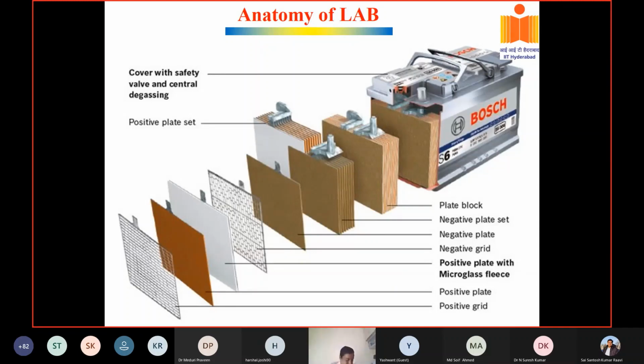The weight is significantly less in the lithium ion cell actually. So this is very light, and if you see here, this is around 20 micron aluminum foil, and around 100 micron is coated. Whereas in the lead acid, the grid itself is around 3.4 or 3.5 millimeter thick, and the lead active materials are coated onto it. Okay, I'll discuss all about it actually. In between, we put a separator. I'll just show you in a minute.